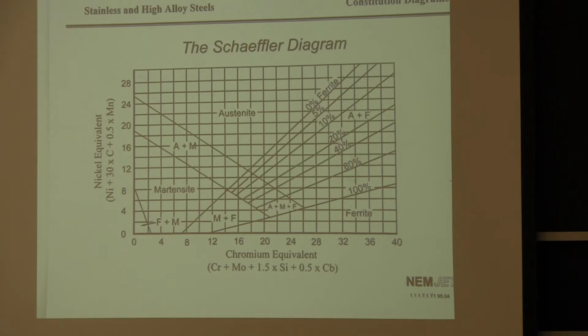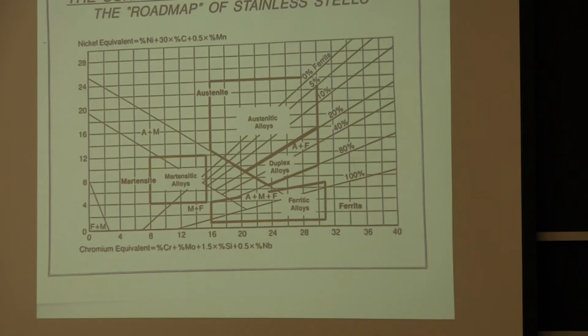And so you can use this diagram. You can take the composition of the steel that you're going to be welding on. You can plot it on these axes here, and what you'll find is that your alloys are going to fall in various regions depending on your composition. And so up here you'll have the austenitic alloys, and like I mentioned earlier, these lines here are called isoferrite lines. So this region over here is completely austenite, or it's 100% austenitic structure. But these lines here tell you that you've got maybe 0 or 5% or 10% ferrite in that structure.